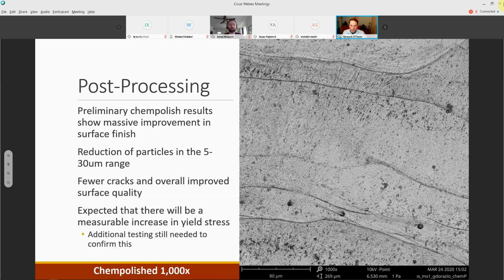So this chem polishing procedure is using an acid bath to remove these particulates. And so the preliminary chem polish shows a massive improvement in surface finish. We had a huge reduction in particles, almost none that we could see in the 5 to 30 micron range, and fewer surface cracks. And we would expect that we could see a measurable increase in yield stress.